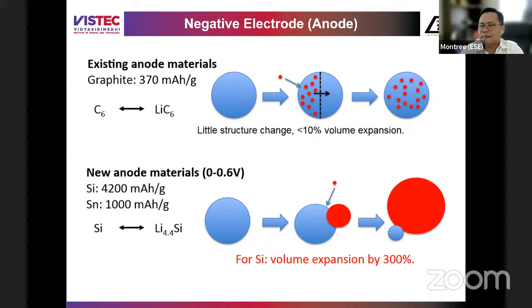Usually like silicon. But when people, for example, Bangjak companies, invest in a startup company in the US, they use silicon, but not yet in the commercial because the big issue of silicon anode, even though it gives you really, really high energy, you can see that it is over 11 or 12 times higher than graphite, but volume expansion over 300%. So the lithium and the active silicon become the alloy. So it can be exothermic reaction if you have side reaction. It's not like graphite. Graphite just intercalates, right?